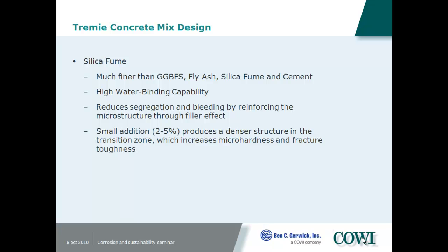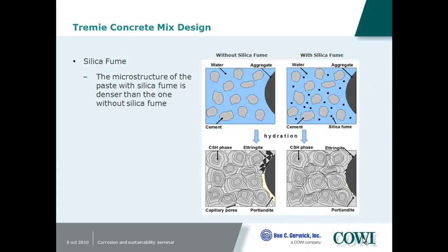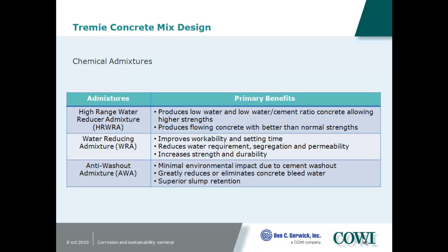Microsilica fume, it's much finer than all the other particles, so it can promote many sites of nucleation for the hydration product to grow, which winds up with a finer microstructure. It has a nice water binding capability. It can reduce the segregation and bleeding, and small additions produce denser concrete with a better bond to the aggregate. It can decrease some of the calcium hydroxide that can be a weaker product. So this just gives you an idea that it gives you a lot more nucleation sites, so it can be a finer type of cement paste structure. It gives you better strengths and better permeability values.